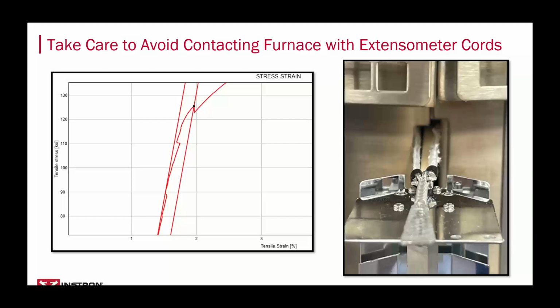One challenge, though, that I want to point out, and it's associated with this extensometer being used with improved efficiency furnaces. The best way to improve the efficiency of a furnace is, of course, to limit as much as possible opportunities for heat to escape. This includes reducing the opening where a side entry extensometer enters. If you're not careful, the nylon cords that hold up the extensometer can rub against the refractory of the furnace.